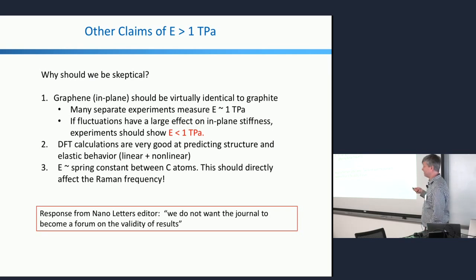A couple other things. One is DFT is pretty darn good. It always has problems with things like band gaps, but for structure and for basic energy, it is extremely good. And especially if you look at our higher order modeling, it fits our data extremely well. It predicts breaking strengths, all kinds of stuff. If it were that wrong to predict a Young's modulus of 1 terapascal where it should be 2 or 7, then quantum mechanics would have some real problems and we would have noticed some other cracks in the foundations of all of solid state physics.